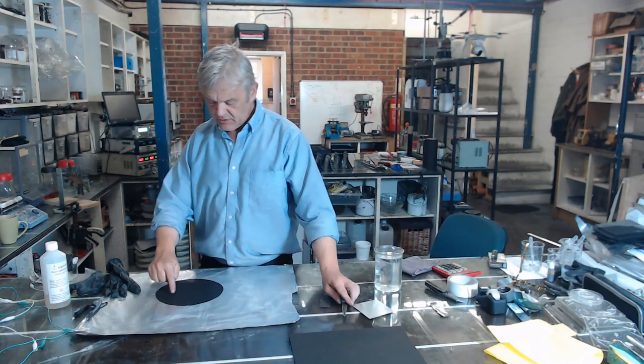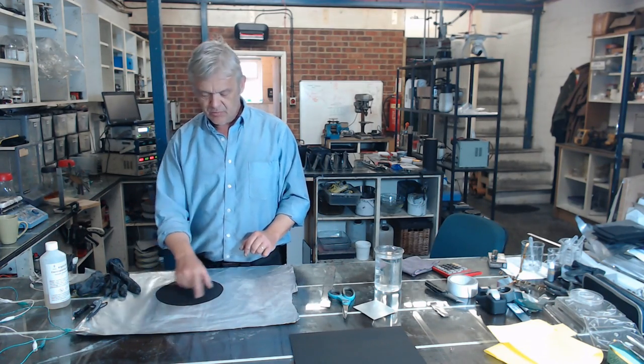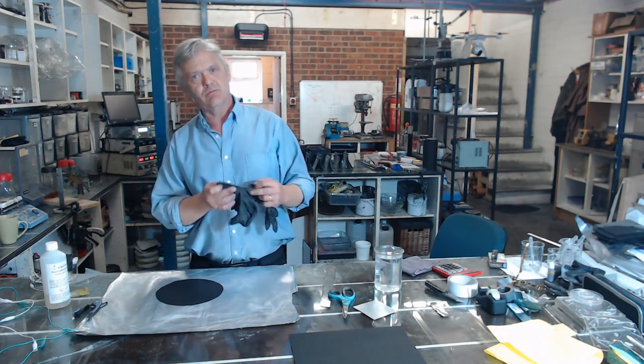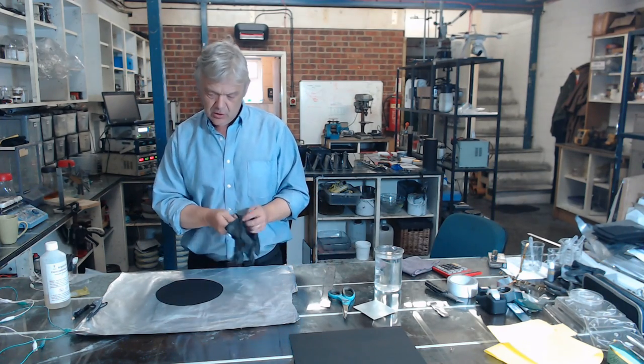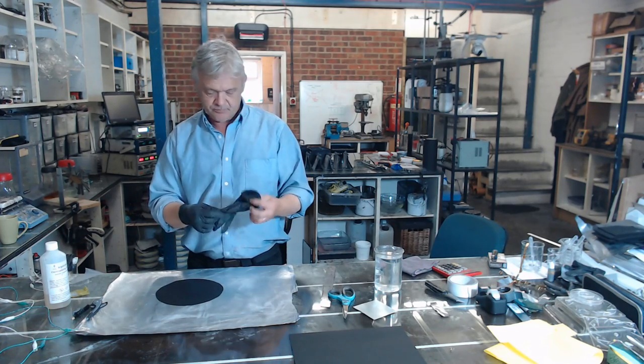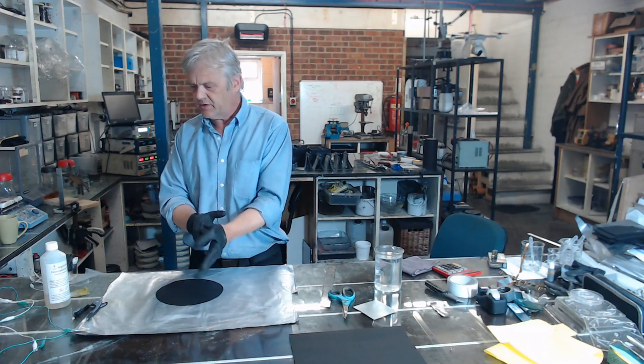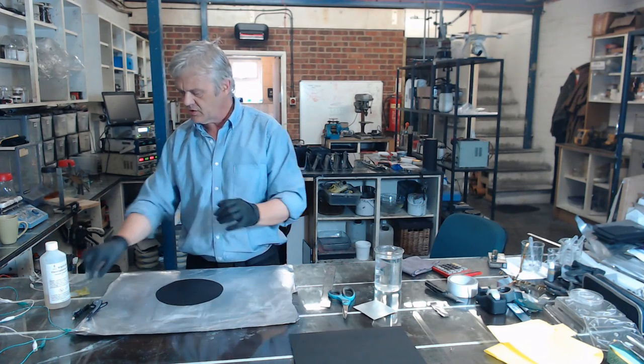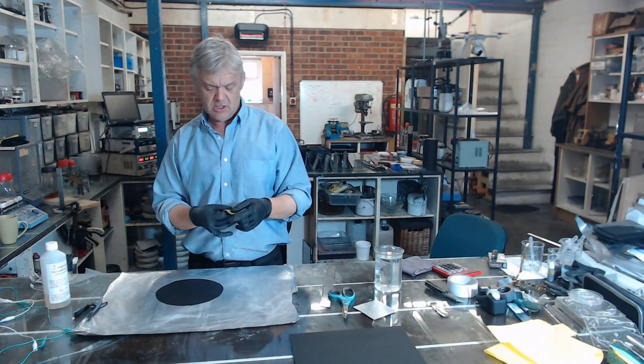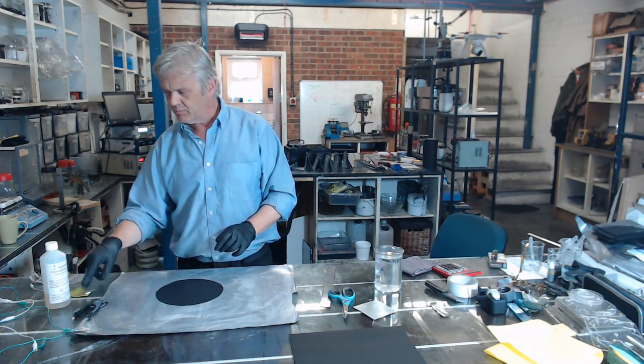What I need to do is electroplate or zinc-coat that bit around the edge — the centre doesn't matter, the bit around the edge is the bit I need to coat. I've done a video on wand plating if you want more detail. In order to do that, I've set up my ground plate and connected it to the negative. I'll be connecting the zinc to the positive. Here's a strip of zinc wrapped in a little bit of cloth that I'm going to use as my wand — I'll wrap it around my finger and rub it on that, connected to the positive.